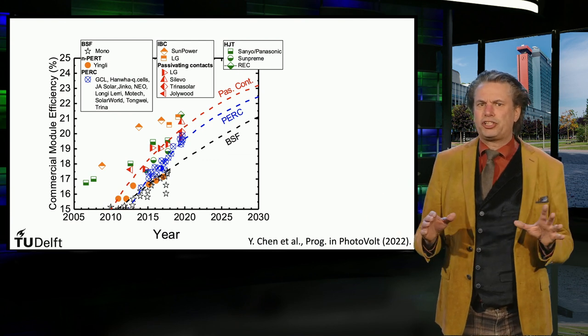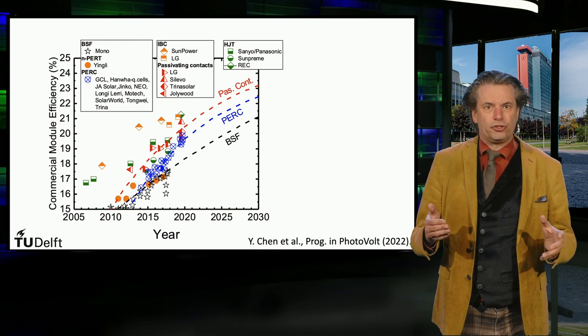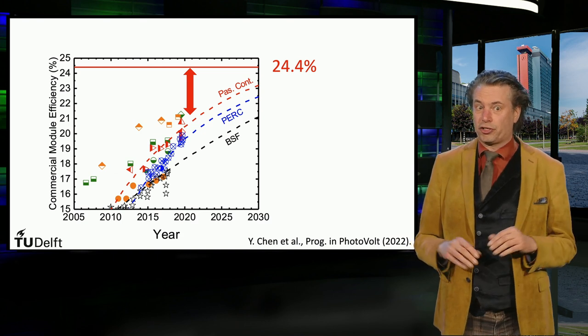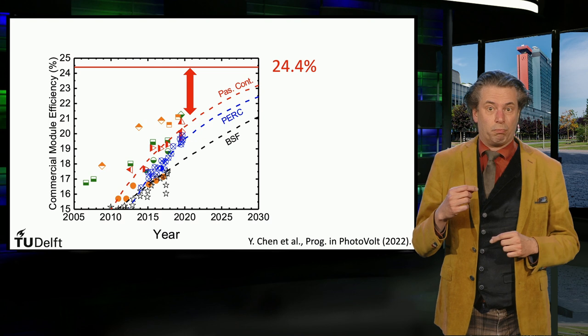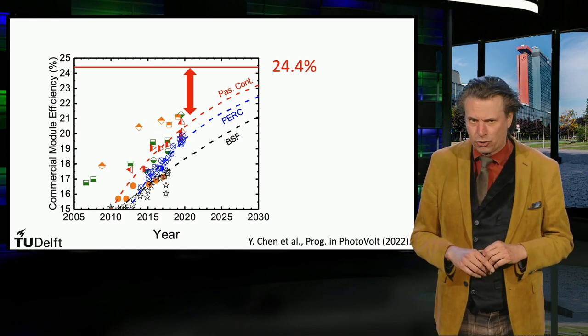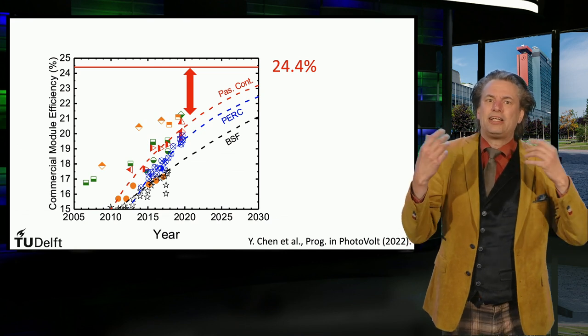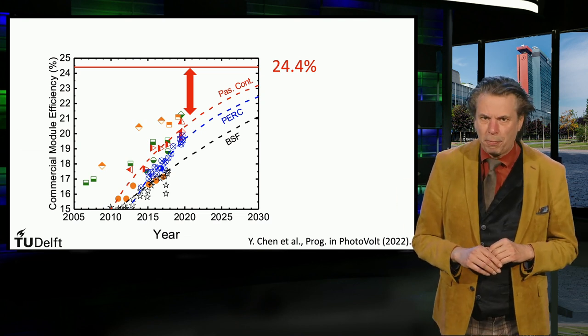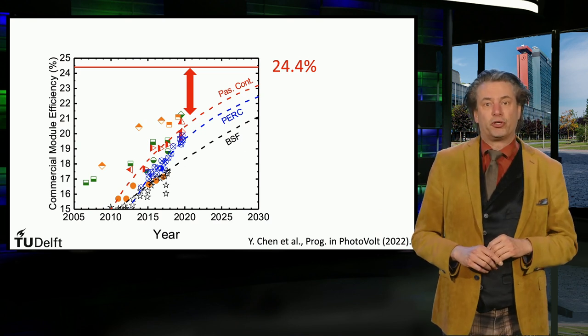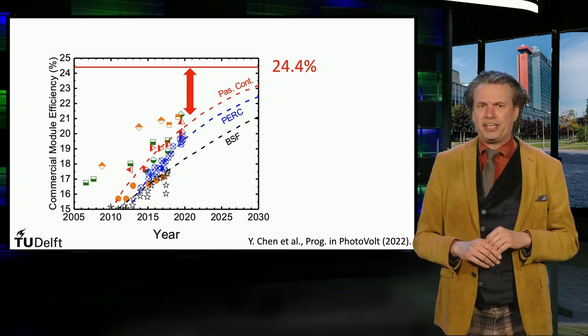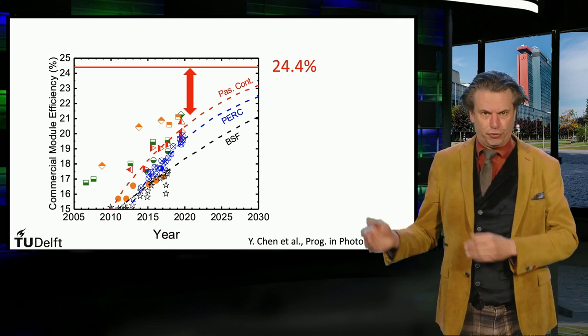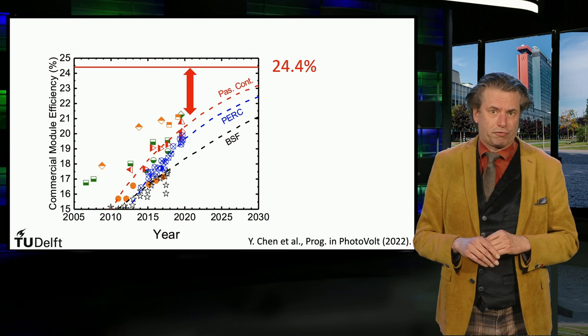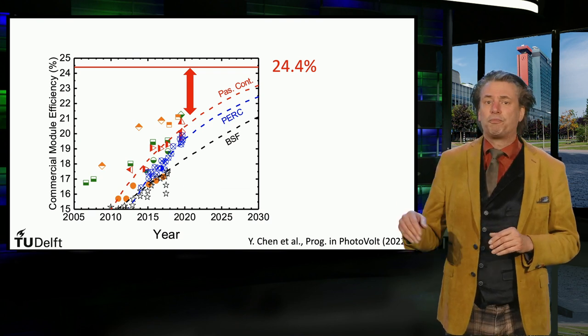As can be seen, the technologies are still advancing and the evolution of efficiencies does not level off yet. If we project these efficiencies versus the demonstrated record efficiency for crystalline silicon modules based on the heterojunction technology, as demonstrated by the Japanese company Kaneka, we see that still a lot of room for improvement exists. Using the earlier introduced simple model, we can make a prediction on the advances of commercial crystalline silicon modules in the near future. A rough estimation is that commercial crystalline silicon modules will see a further absolute improvement of conversion efficiencies in the order of 2–3% up to 2030.